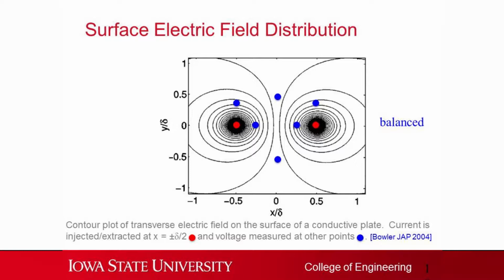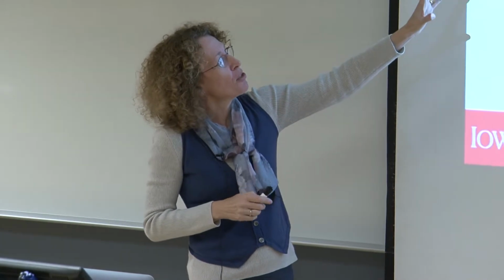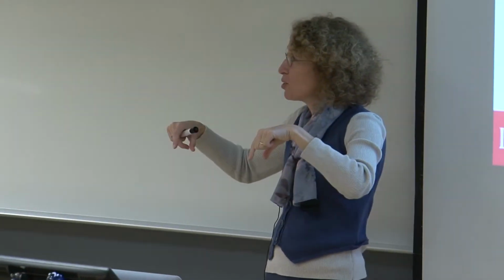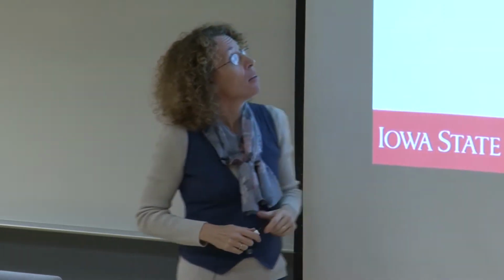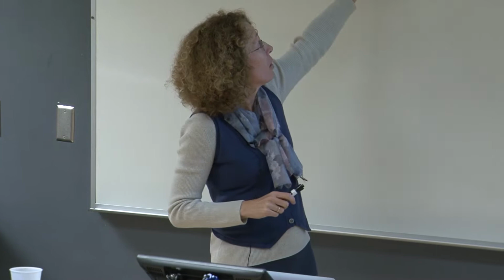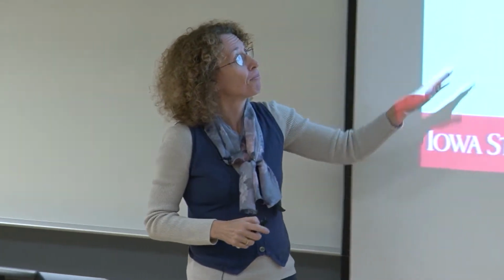Okay, so that voltage, and this is all fairly simple in terms of its physics, that voltage that we're measuring then is determined by how you arrange your probe points. It's also determined by parameters of the test piece, its conductivity, permeability, and also geometry, and also presence of defects and so on. So in terms of geometry, we could think of a flat plate type geometry. We could think of cylinders. And in fact, one of the examples I have is looking at the properties of crankshafts that are hardened for improving their resistance to wear. So if we properly interpret this measured signal, then we can find out something about the test piece.